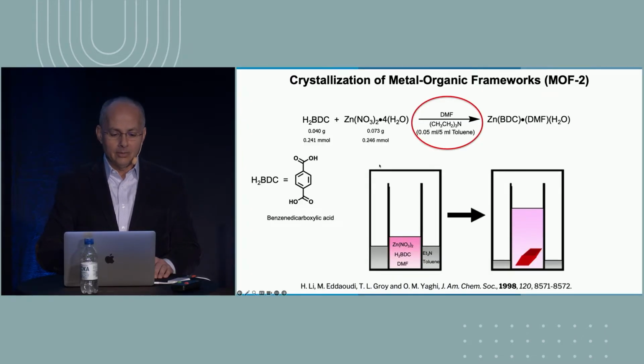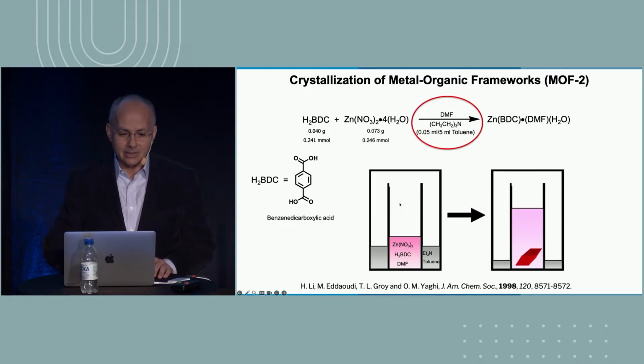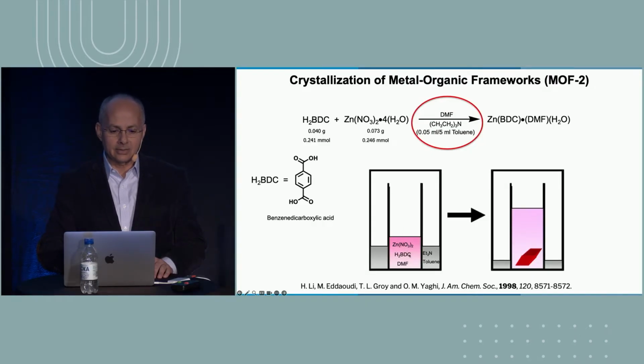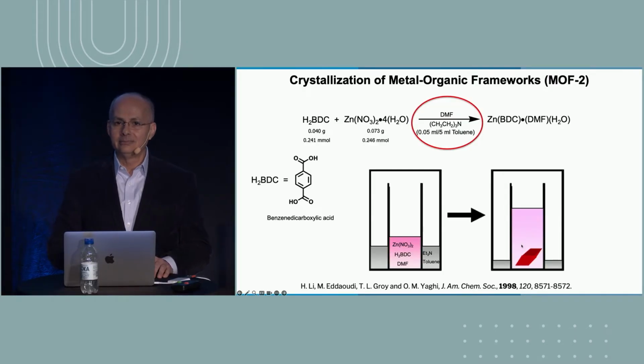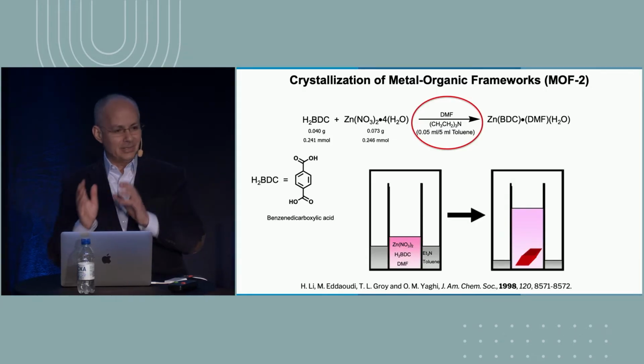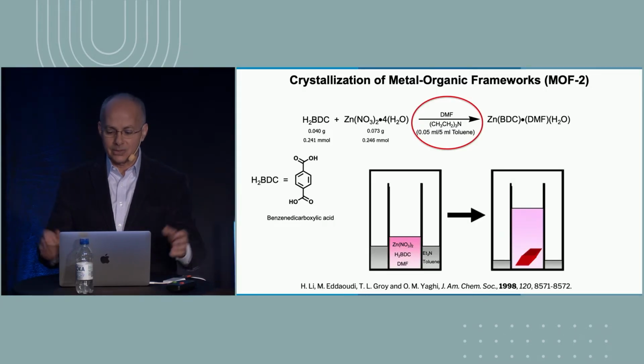Okay? So he did a classic crystallization. Here is a solution of zinc nitrate and the acid in DMF, and now you've got your base in toluene that diffuses in slowly to make a crystal. Okay, very simple reaction, very simple strategy to make sure it was successful.